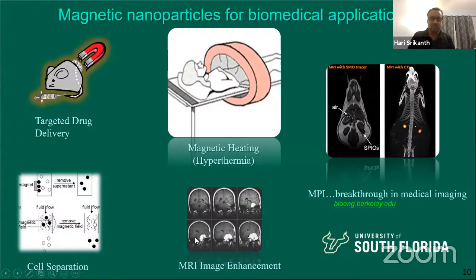A second area where there's a lot of effort and magnetic nanoparticles have made a huge impact is that you can use these magnetic particles for improving the contrast in MRI images. MRI is magnetic resonance imaging. It's very commonly used in hospitals, and it's based on NMR. Most biological tissue contains water. So you can excite the water protons, let them precess by applying a DC field and a high frequency oscillation. Then you remove the field, they relax. And from the relaxation time, you get images like these. From the T2 relaxation time, you can get these images, and that's your standard MRI image.